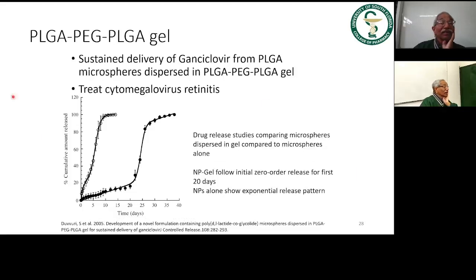So then if you use PLGA-PEG-PLGA gel, you are looking at two polymers there. You will find that the drug release can continue over a period of almost 35 days. So now it is going one month. Now you have to understand that all these studies are done in 10 ml to 20 ml of dissolution solution. But in the eye, there is never 10 ml solution available. The eye capacity is only 0.5 ml or maximum 1 ml, and 1 ml is also very difficult. So obviously this can be extrapolated to many more days.